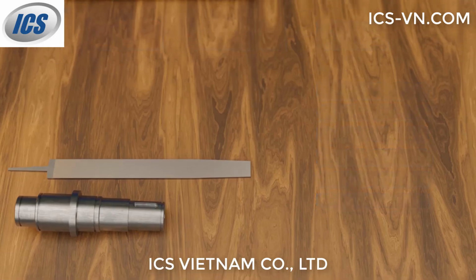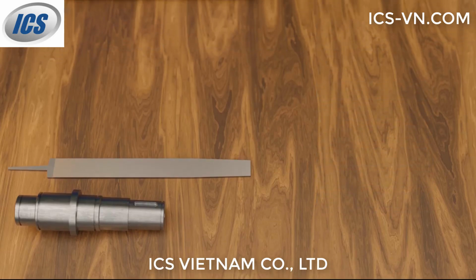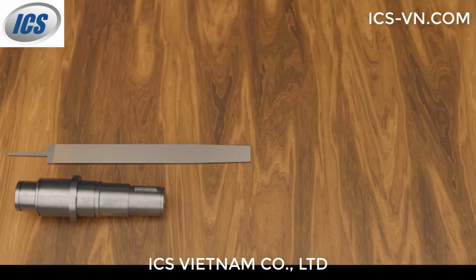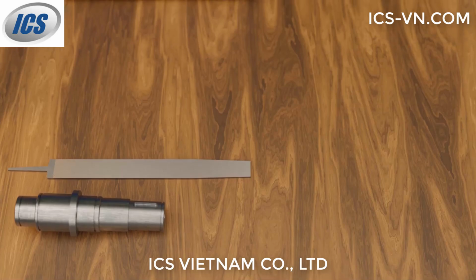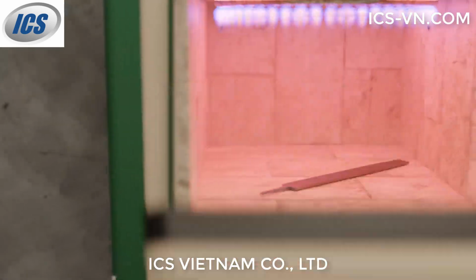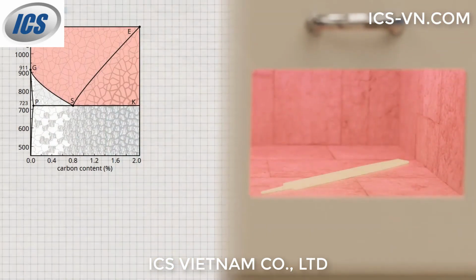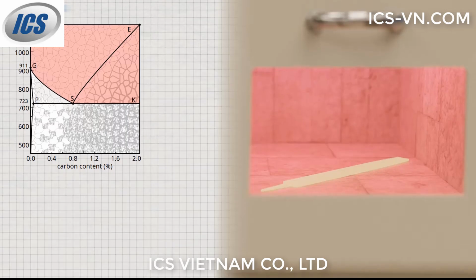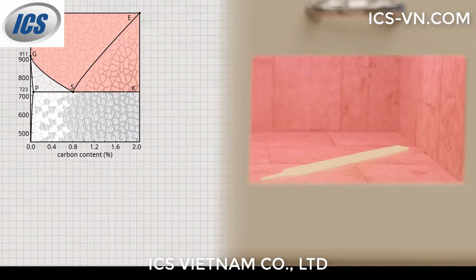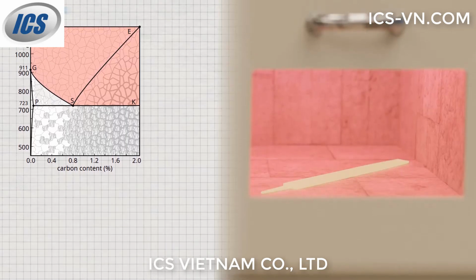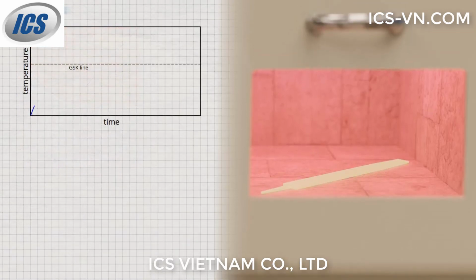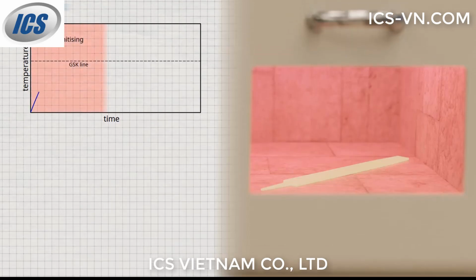The microstructural changes of the steel during the individual steps of quenching and tempering are discussed in more detail in the following. As mentioned before, the first step is to heat the steel above the GSK line in the iron-carbon phase diagram. This completely transforms the body-centered cubic ferrite lattice into the face-centered cubic austenite structure. This is why the process is called austenitizing.